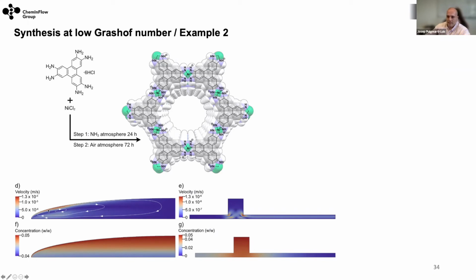But what happens, these are numerical simulations, is what you see here. Natural convection will evolve. So you can have the precipitation of some crystals here, they will fall, they will deplete the reactant, you will generate convection. And then what you see is that the diffusion of the reagents goes in favor of gravity. And this is what you have in our microfluidic device.